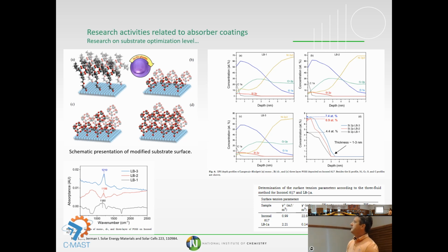So we made a plasma treatment in order to increase the reactive sites on the surface. Then we applied, for instance, epoxy-modified polyhedral oligomeric silsesquioxanes. We made FTIR analysis to confirm that those silica molecules are there, in addition to XPS. We produce those layers by Langmuir-Blodgett films. You put your molecules on top of water, for instance, and compress them together to produce a really dense film, and then you transfer everything onto the substrate. We cure, and as you could see, the thickness was very low. At the beginning it was mainly silica, and then after you could see the substrate, like nickel, chromium, and so on, and oxygen, which is low.